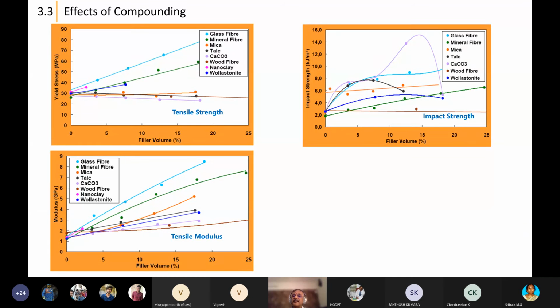This is on the impact properties. You can see a very good one, calcium carbonate up to 15% filling improves the impact properties. But the moment you cross 15%, the impact properties start falling because till 15%, it fills all the molecular gaps and helps the polymer transfer the impact energy so that it is able to withstand the impact. But after 15%, it becomes a mere filler and it causes the impact strength to drop. But with glass fiber, there is a steady increase. After 15%, you see a steady increase. In mineral also, you will see a steady increase. Wollastonite, there is a drop after 15%.